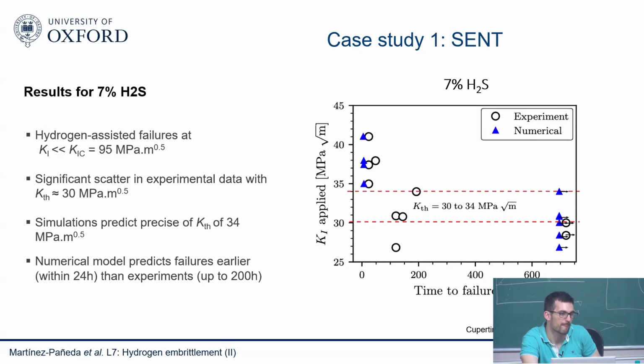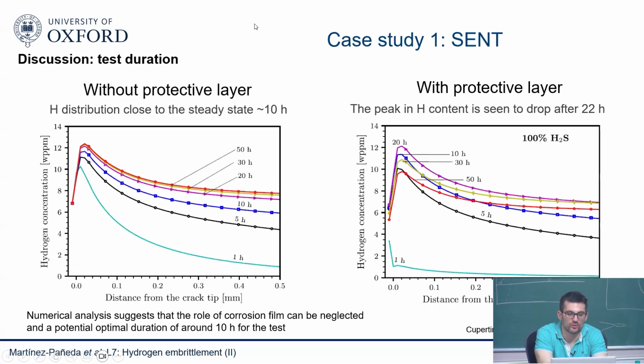KTH should be more than KIC, no? Like once the crack is initiated, then only it will stop after some time. Well, I think for this case it's simpler to think of it as K1C. It's used as a K1C criterion. We don't look into subcritical crack growth much in this case. Yeah. So then we use the experiments to interrogate the model a bit.